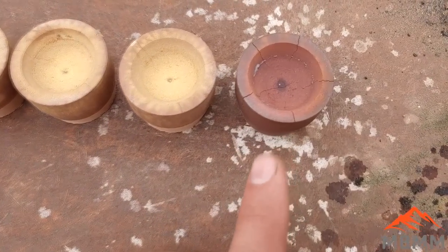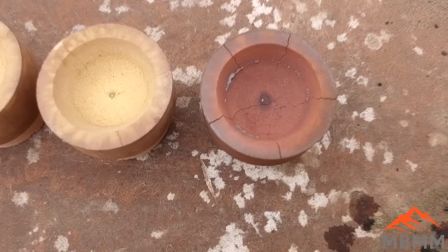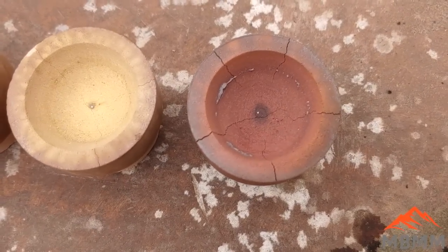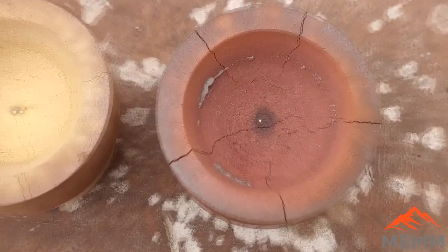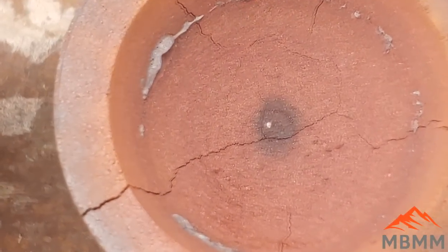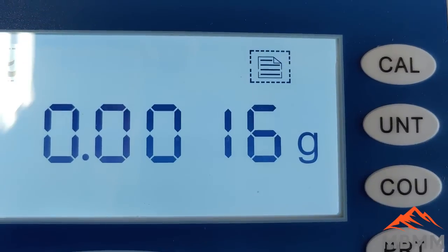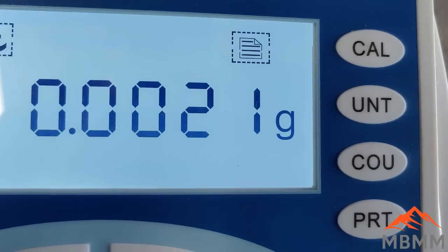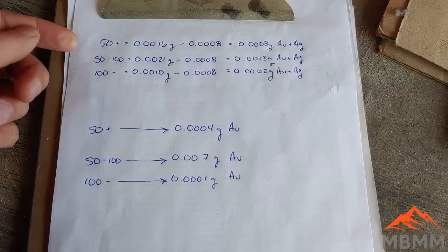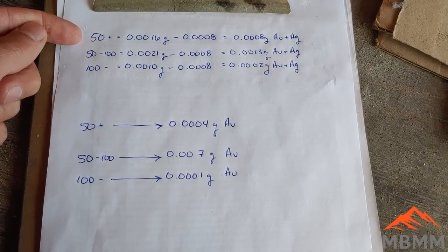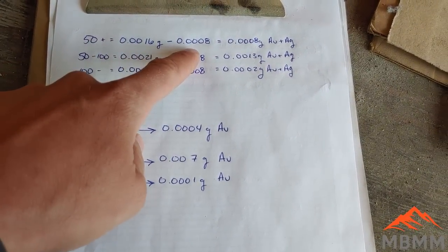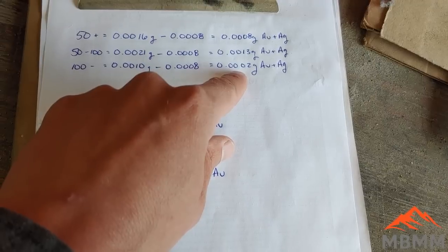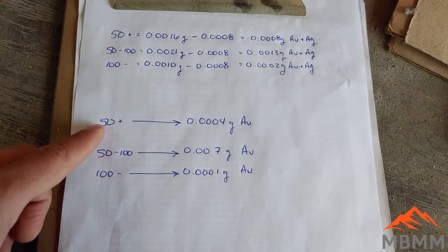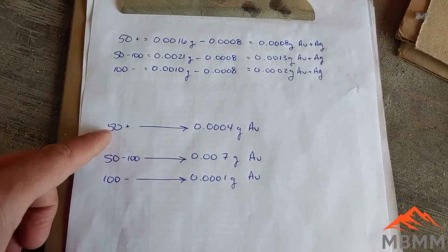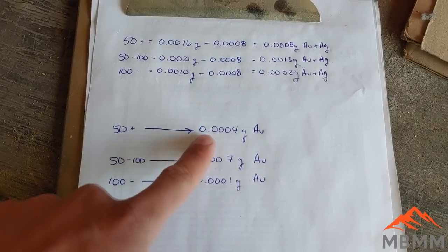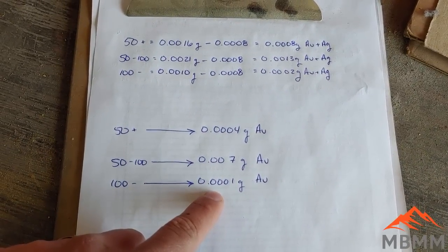But this cupel I just did, this is our blank lead sample. And you can see there is a little bead of precious metals in there. Here's our 50 plus, 50 to 100, and our 100 to 200. So here's our screen tailings fractions. There's the weight of the bead, subtract the collector metal, and here's the weight of our beads in gold and silver. And then down here I've taken out roughly half of the gold and silver based on our XRF reading. And so you can see where most of the gold is in the tailings.